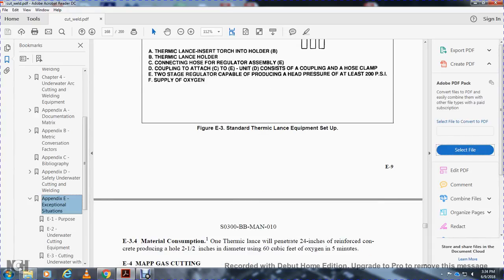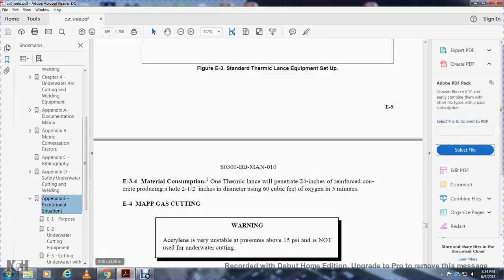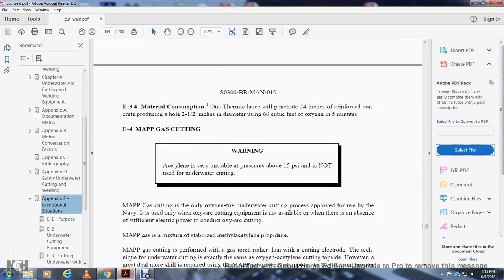E3-4, material consumption. One thermic lance will penetrate 24 inches of reinforced concrete, producing a hole of 2.5 inches in diameter, using 60 cubic feet of oxygen in 5 minutes. E4, MAPP gas cutting. Warning: acetylene is very unstable at pressures above 15 psi and is not used for underwater cutting.